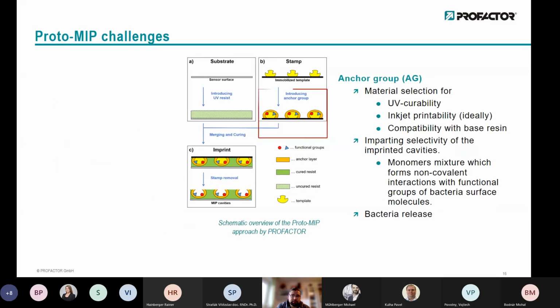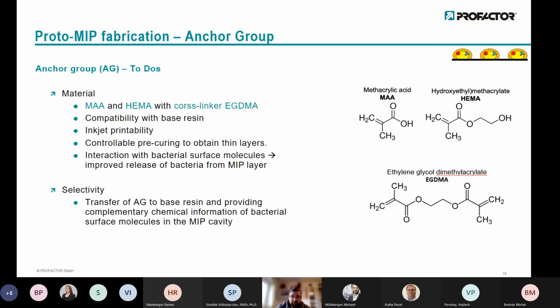The second challenge is indeed to introduce the anchor group. So in order to identify, there are two things basically. On the one hand, to identify the suitable anchor group, and that it's also linkable to a UV resin. So the natural thinking is to use a monomer that can be polymerized in the same way as the UV resin, so basically an acrylate. So with this, we played out with different monomers, also mixtures of them, adding photoinitiators to pre-polymerize to not just have monomers but oligomers, and selected them by the potential linkage, respectively potential affinity to the bacteria surface. So therefore we went for, let's say, more hydrophilic approaches than hydrophobic molecules here.